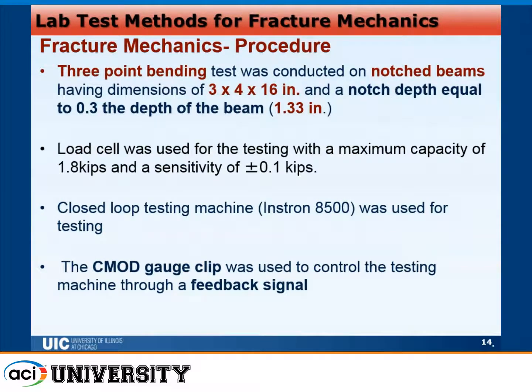For the testing procedure, we prepared 3 by 4 by 16 beams, notched as per the RILEM recommendations at a depth of the specimen divided by 3, so it's equivalent to 1.33. A load cell of 1.8 kips was used for high sensitivity, because these samples are notched and do not take higher loads to initiate the crack. So we decided not to use the 50,000 pounds load cell because it has lower sensitivity.